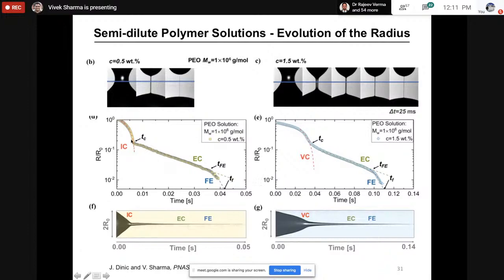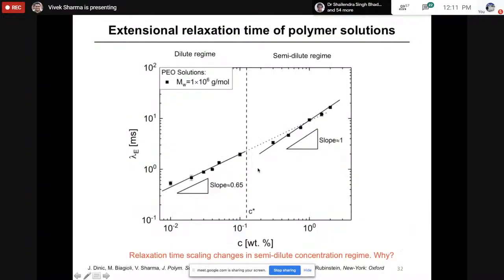We can analyze many things from here, but the key thing that we really look for is the relaxation time extracted from the elastic capillary regime. And what we find is the elastic capillary regime gives you less than a millisecond time scale. This time scale is too short to be measured on even the more expensive Caber as well as the torsional rheometers. So these are some of the shortest time scales that can be measured. And there's a distinct transition from a slope of 0.65 to a slope of 1. The concentration dependence changes above C star, more or less.